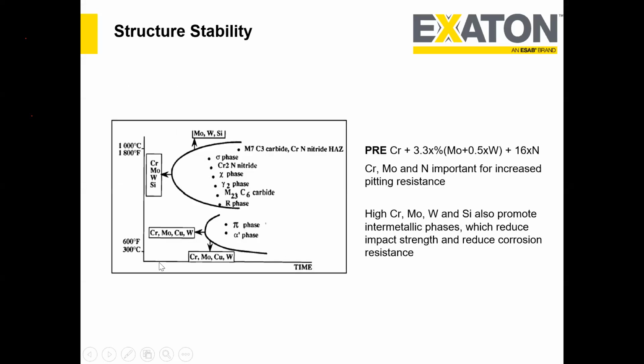This is a little bit of an interesting graph. What this graph says, as I mentioned, is that the higher the alloy element content, the more susceptible it is to forming this kind of intermetallic phases. You see here chromium, molybdenum, tungsten, silicon. These are the alloy elements present in the duplex. The higher the content of these alloy elements, the upper C curve moves to the left, and molybdenum, tungsten, and silicon also move it in the upward direction.